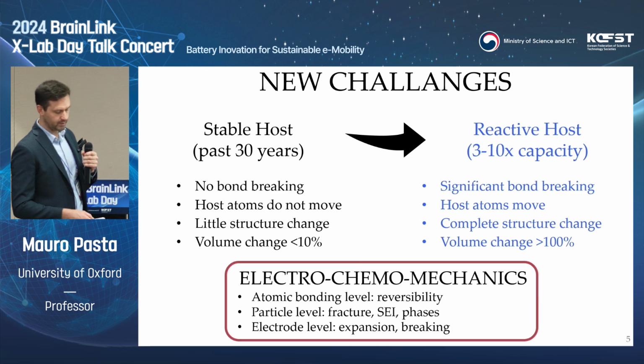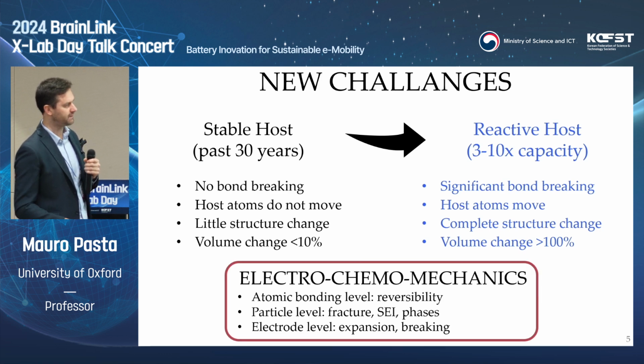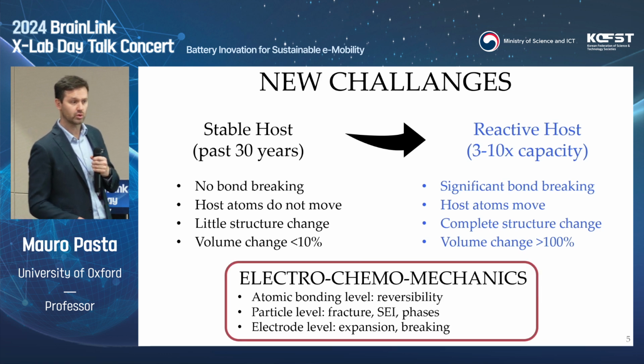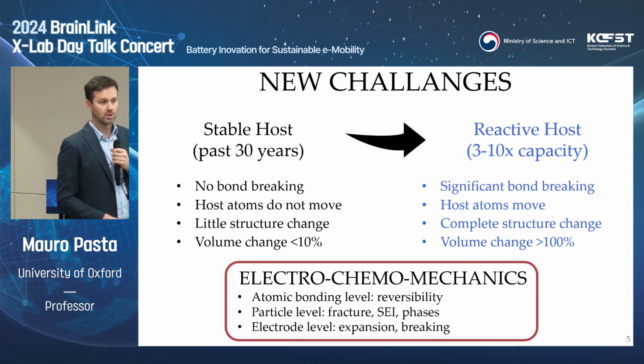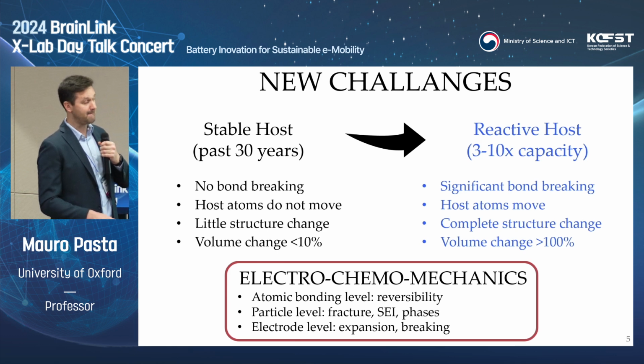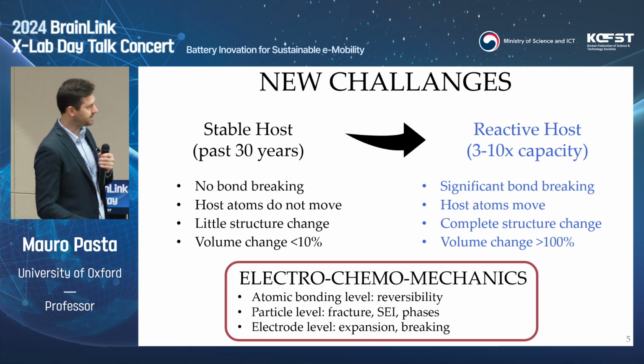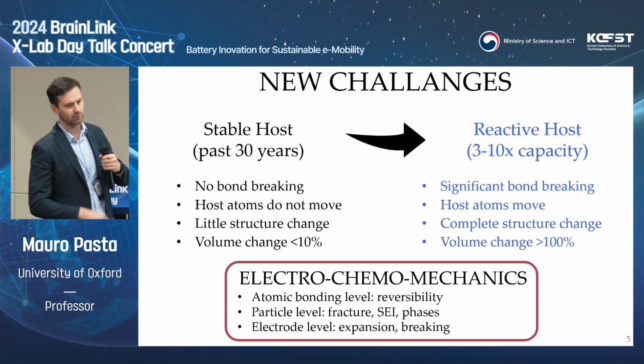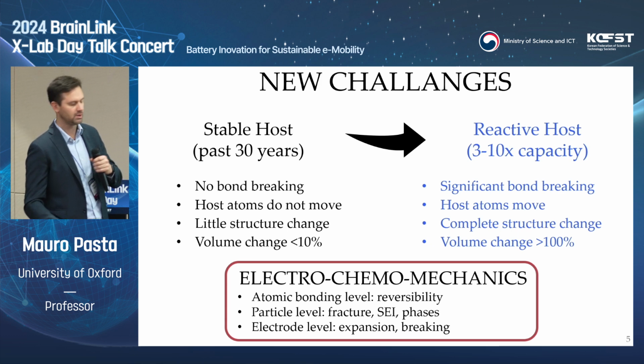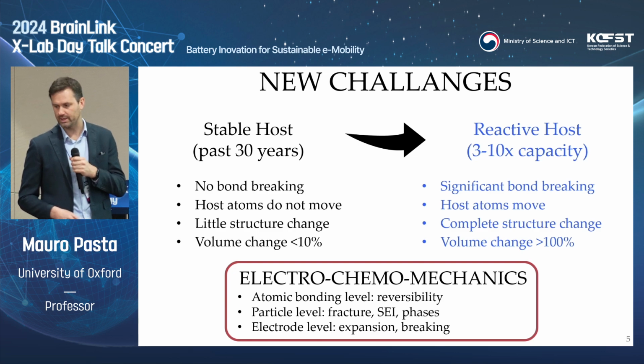And therefore, the new field in the past 10 to 15 years that has become quite prominent and important is the field of electrochemo-mechanics. So electrochemistry, chemistry, and mechanics together to understand mechanism of conversion as well as degradation mechanisms that are affecting both problems at the atomic level with reversibility, at the particle level, fracture of the particle, SEI formation, new phases forming, as well as the electrode level with expansion, breaking, and contact retention.